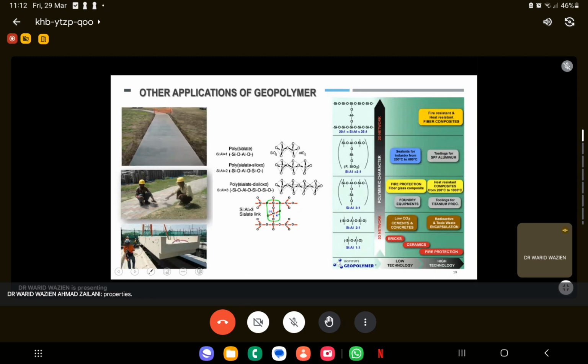If you can see, when the silica to alumina ratio is getting low, the resulting geopolymer matrix tends to be more aluminous, and which can lead to a material with high mechanical strength but low chemical stability in aggressive environment. So yeah, it's often suitable for the structural application where the high strength is critical, but they may not perform as well in acidic environment. So kat situ bila we are talking about the environment yang beracid dan beralkali dan sebagainya, so we need to adjust the silica to alumina ratio.